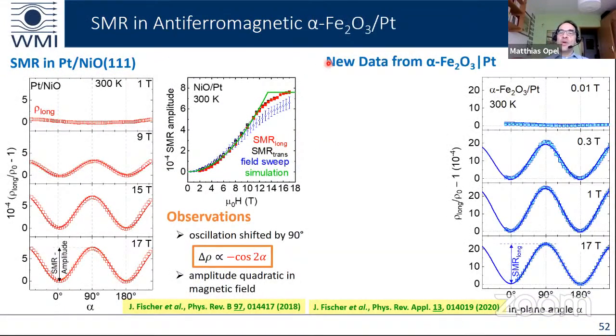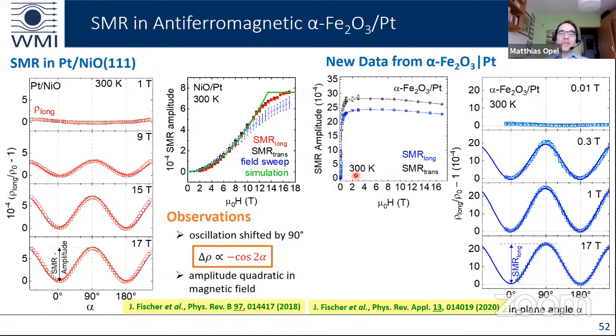I want to show you the newest data from hematite, another antiferromagnet with platinum, and it shows the same oscillations, minimum at 0 degrees and maximum at 90 degrees. But we see that the SMR amplitude increases much faster and then saturates around 3 Tesla.